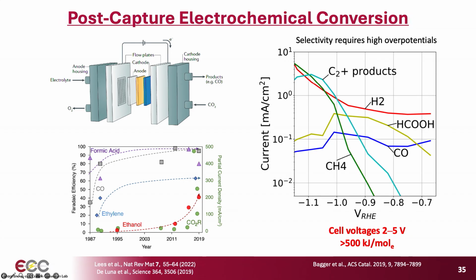So these work by taking CO2 as an input, doing an electrochemical reduction reaction to various products using water or protons as a co-reactant. And then the opposing electrode does a water splitting reaction and releases oxygen. And nowadays we can run these electrolyzers pretty selectively for a certain class of reactions. So forming carbon monoxide as the product, we can do that generally pretty efficiently. Making more reduced and perhaps more value-added products like ethylene and ethanol, we can do that, but with lower selectivity.